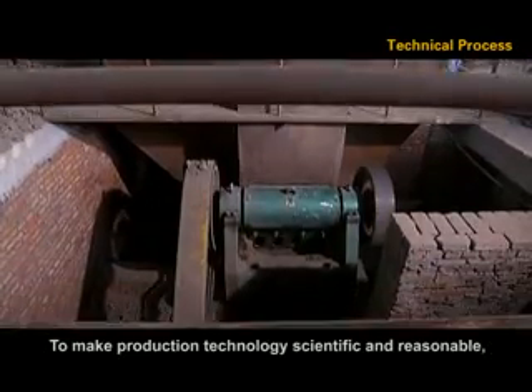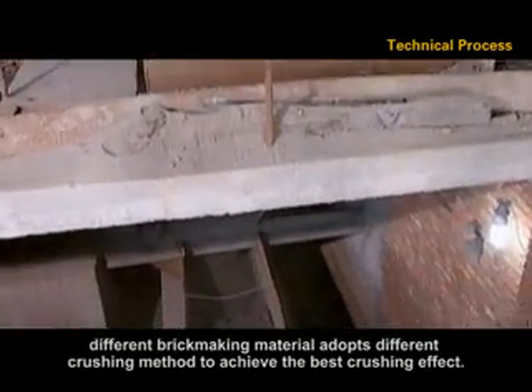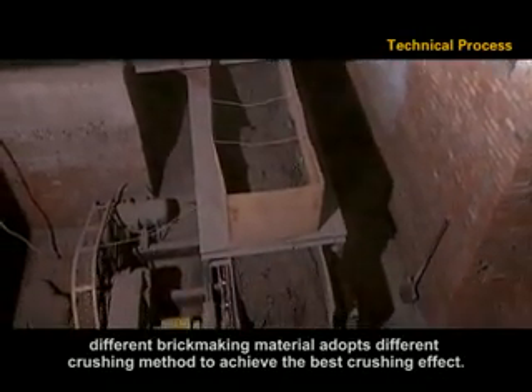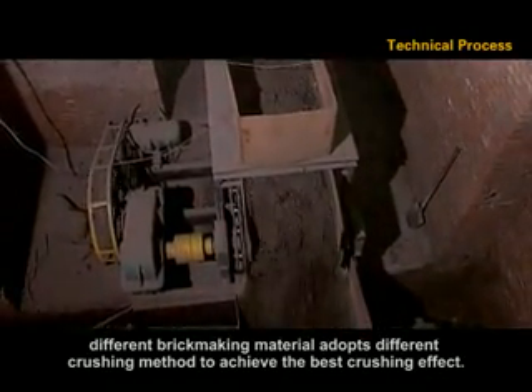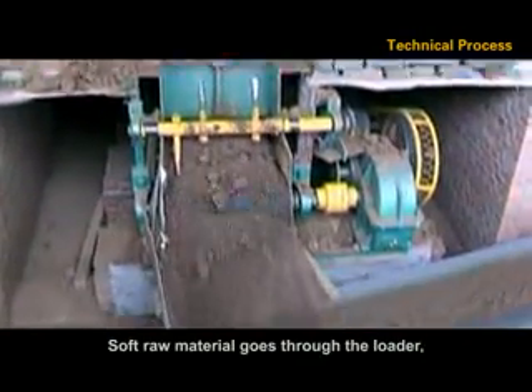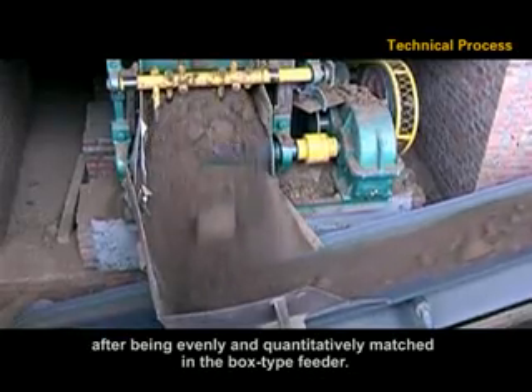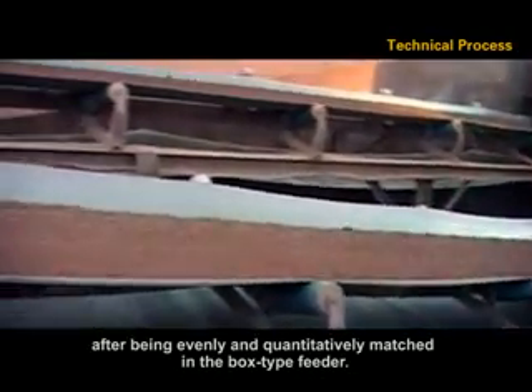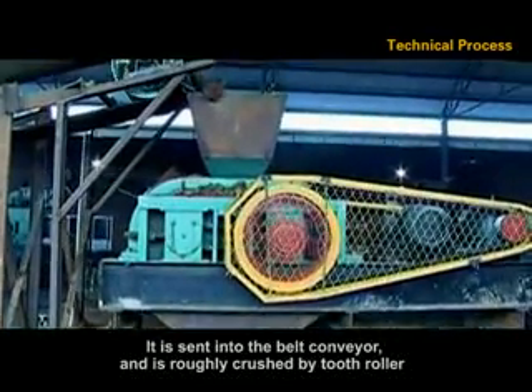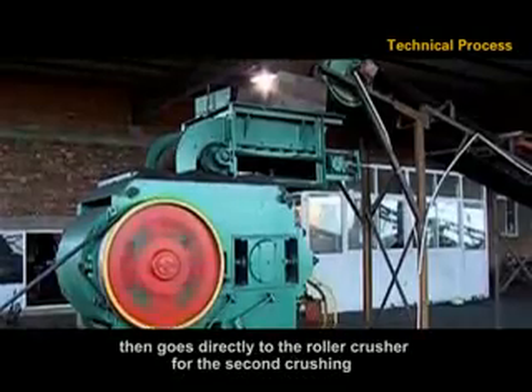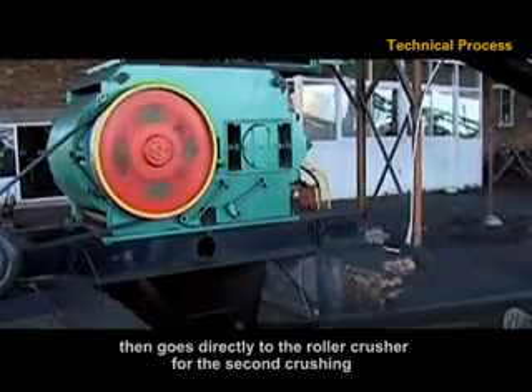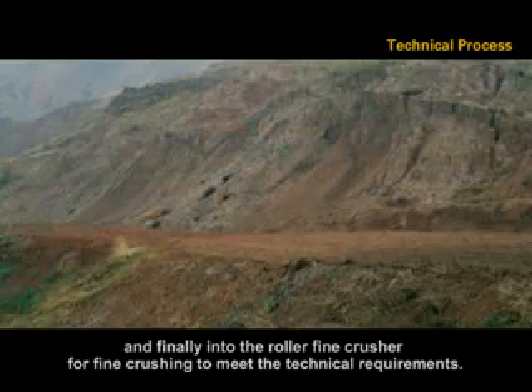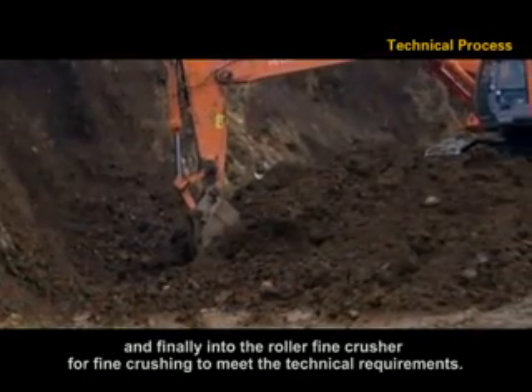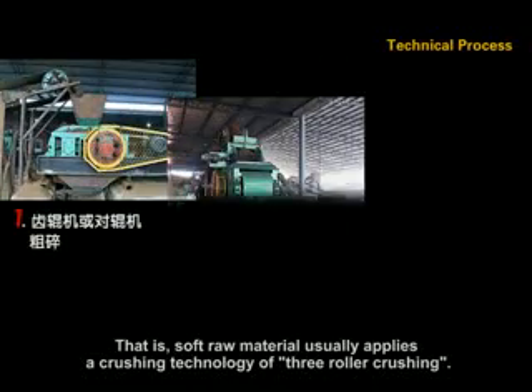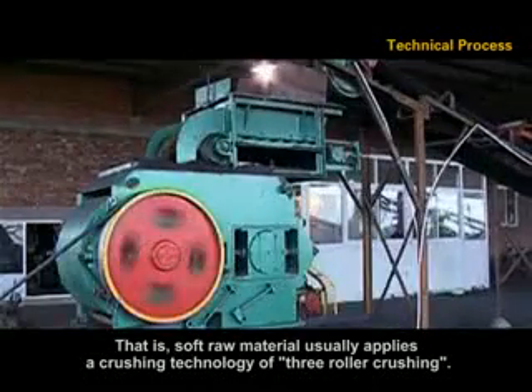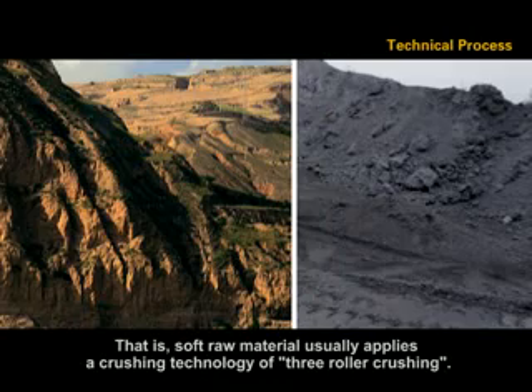To make production technology scientific and reasonable, different brick-making materials adopt different crushing methods to achieve the best crushing effect. Soft raw material goes through the loader after being evenly and quantitatively matched in the box-type feeder. It is sent into the belt conveyor and is roughly crushed by tooth roller, then goes directly to the roller crusher for the second crushing, and finally into the roller fine crusher for fine crushing to meet the technical requirements. That is, soft raw material usually applies a crushing technology of 3-roller crushing.